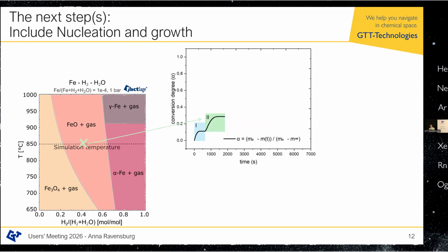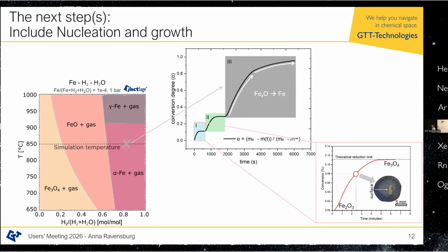So we move our conditions to be in a ratio where it is possible to form wüstite again, and now we move from Fe3O4 to FeO. Again, we converge exactly at the value that corresponds to the mass loss that you would have for 100% wüstite. And then the same thing we can do for iron. Of course, these processes become slower. And if we look at them, for example, at the first step, we can look at these conversion degrees and we can stop them at any time.